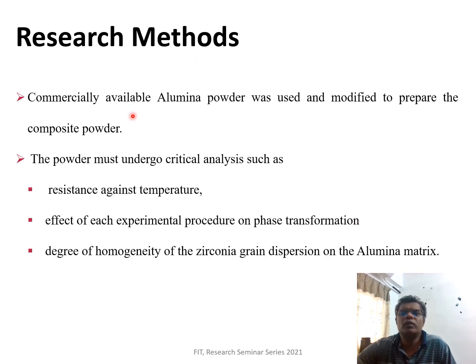So in the development of the green body, first we use the available alumina powder, modified to prepare the composite powder. The powder must undergo a critical analysis, such as the resistance against temperature, the effect of each experimental process, and phase transformation, to be checked carefully. The degree of homogeneity of zirconia grain dispersion in the alumina matrix will be analyzed.